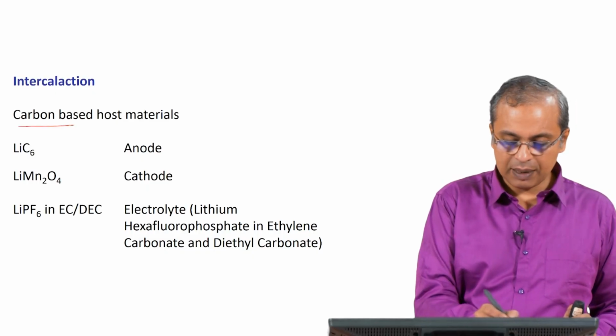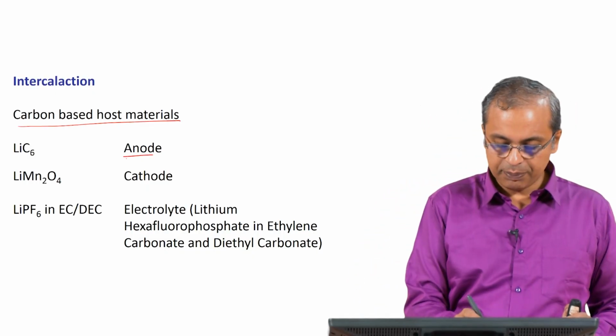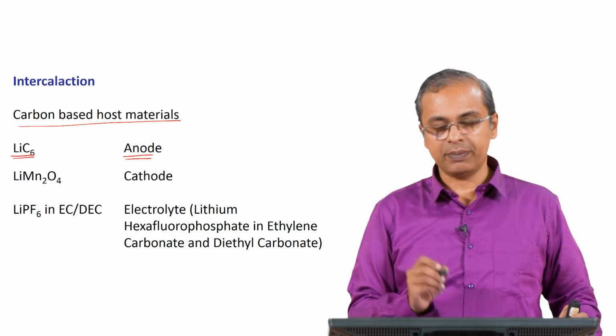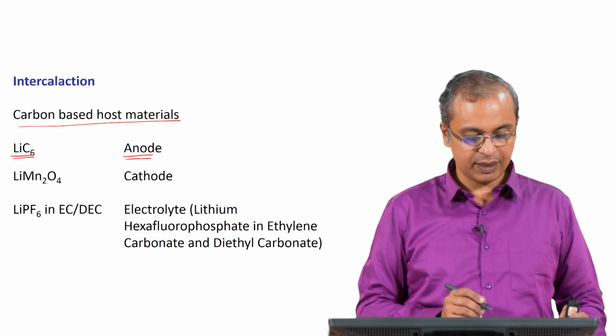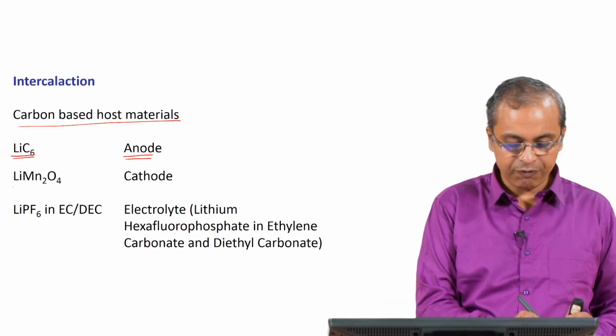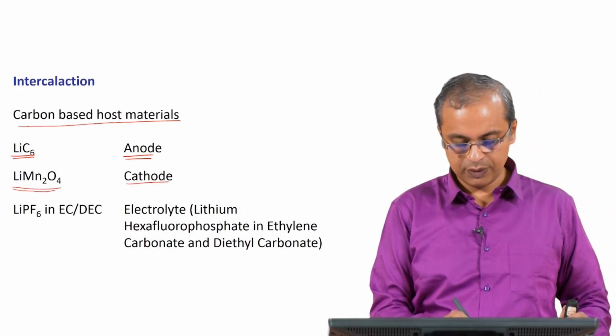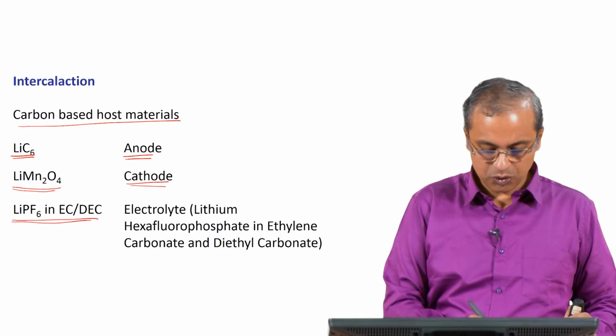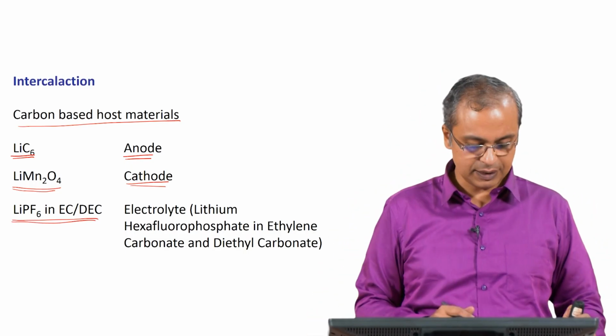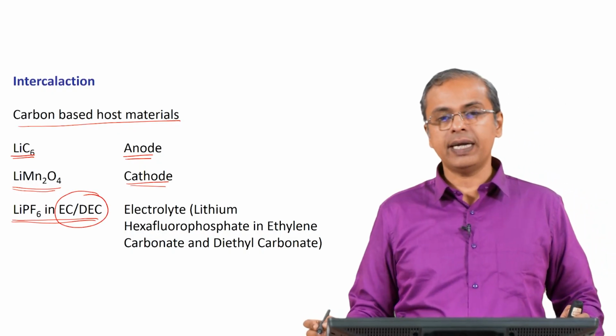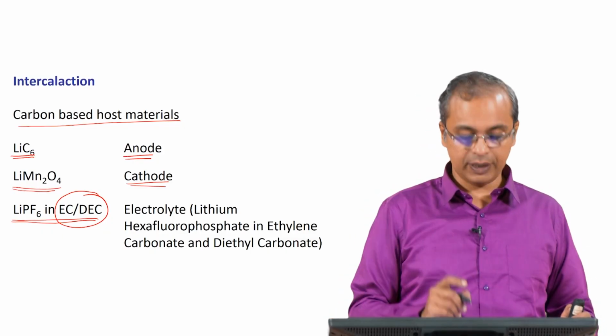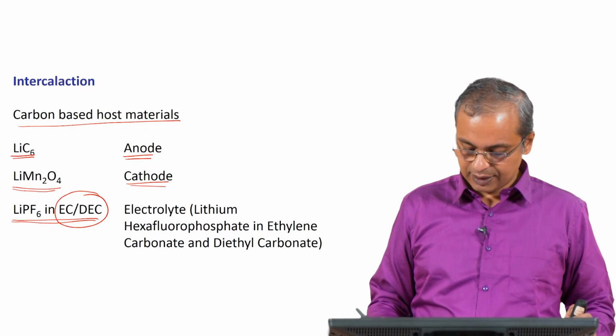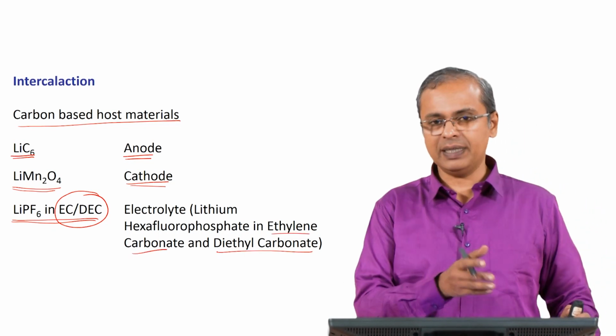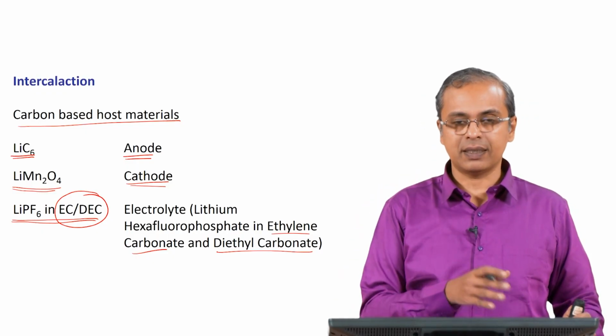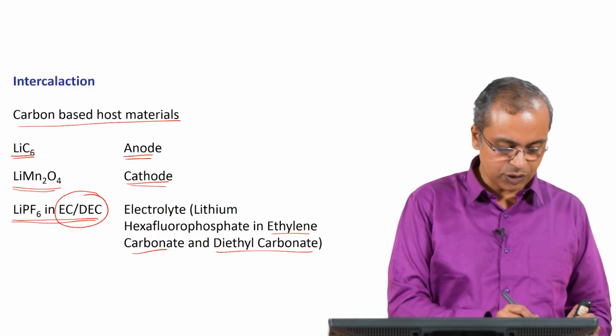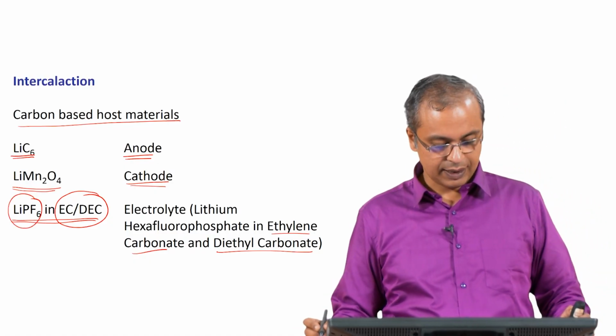So, typically people have now used carbon based host materials for the anode, and therefore, the anode is typically LiC6, a combination of lithium and carbon, and typically graphite is used. LiC6 is the material that is used, and in similar fashion they have lithium manganate as the cathode, and the electrolyte is some salt of lithium. Lithium hexafluorophosphate is what I am indicating here, that is one of the combinations, and that is usually put into some solvent. Okay, and you cannot use water here because water will react with lithium. So, these are some organic solvents. In this case it is ethylene carbonate and diethyl carbonate, but there are various other combinations, dimethyl carbonate is there, various other solvents are also being investigated and used, but it is typically a salt of lithium in some ethylene carbonate, diethyl carbonate kind of thing.